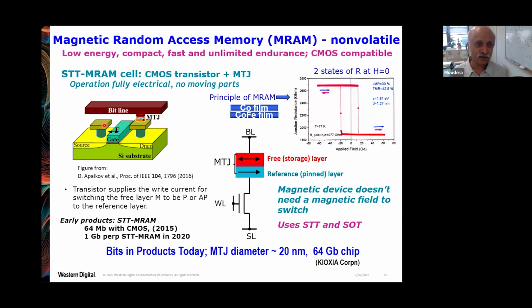And what they have done is they've gone a long way. They are able to have the magnetic random access memory or this MTJ structure in compatibility with semiconductor processing. They have CMOS here, and they have created the CMOS transistor right here, which drives the current through the system, and you have an MTJ. So this current is able to rotate the magnetization from one direction to the other, which means you don't need a magnetic field to switch the magnetization. They use what's called spin transfer torque. That's what they use here.